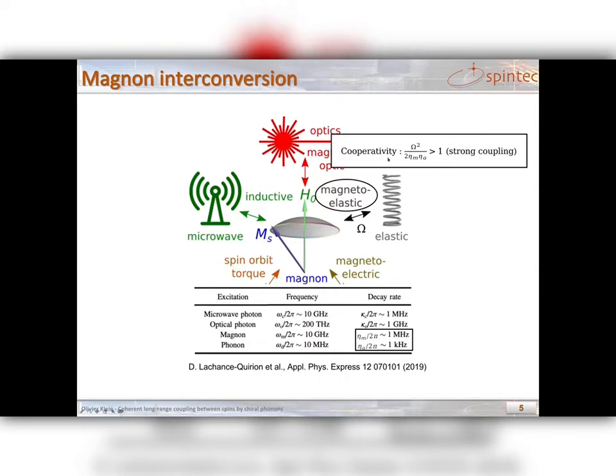What we want to focus on in this talk is the magnon-phonon interconversion. The figure of merit of this interconversion is the cooperativity, which depends on the coupling strength and the relaxation rate of magnon and phonon. And what I will show you is that garnets are a very promising platform to study magnon-phonon coupling, not because the magnetoelastic coupling strength is particularly big, but mostly because the relaxation rates inside these materials, both magnons and acoustic, are extremely low, which leads to a cooperativity that is above 1, which is the signature of being in the strong coupling regime.